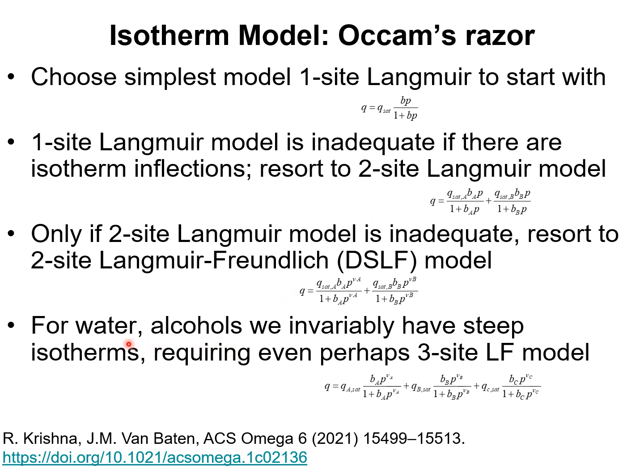For adsorption of water and alcohols within MOFs and zeolites, the isotherms exhibit steep behavior due to molecular clustering, and it may even be necessary to adopt a three-site Langmuir-Freundlich model. Summarizing, keep matters simple, use Occam's razor, choose the simplest model, increase the level of complexity only if this is strictly required.